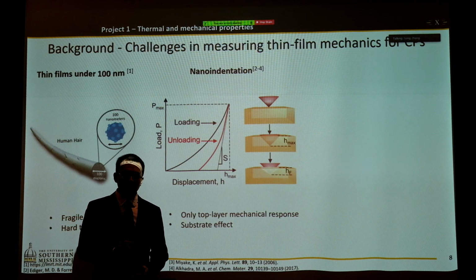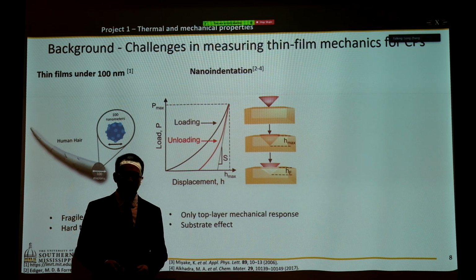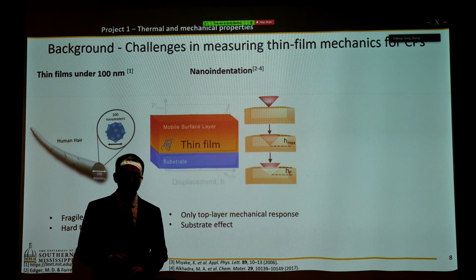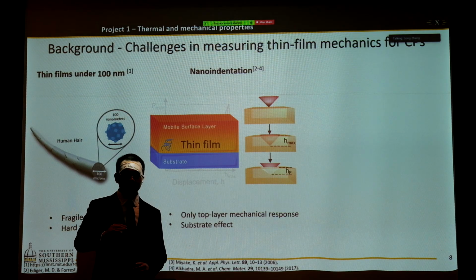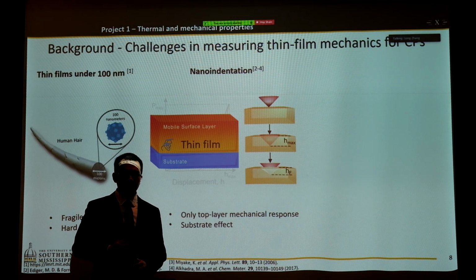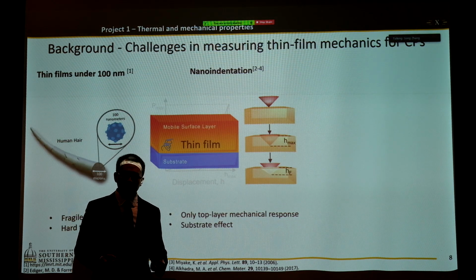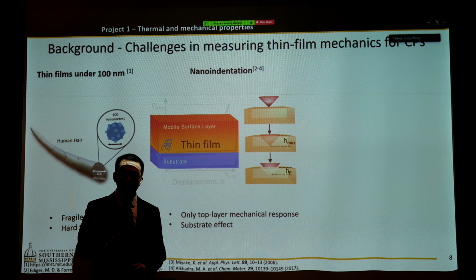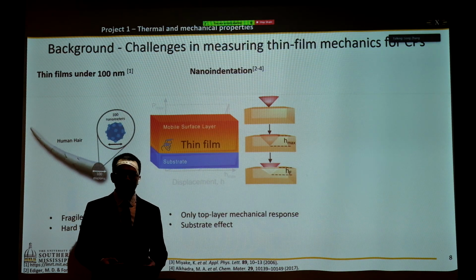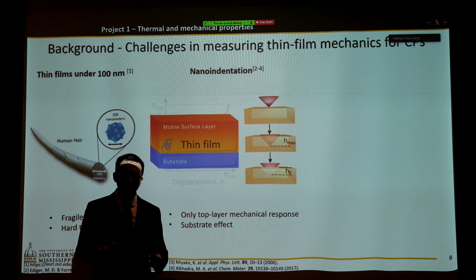And why is that? Firstly, there is no stress-strain behavior. We cannot quantify the interaction area very easily. And secondly, it is already known that there is an intermediate layer between the thin film and air. In that layer, called the mobile surface layer, the thermal and mechanical properties are very different from the bulk film. So with only the top layer mechanical response, you cannot understand the thin film response.